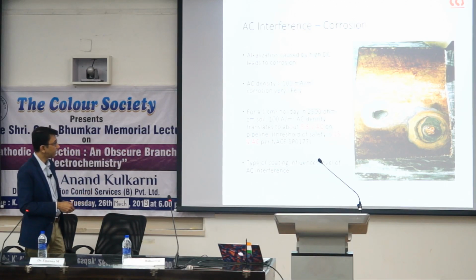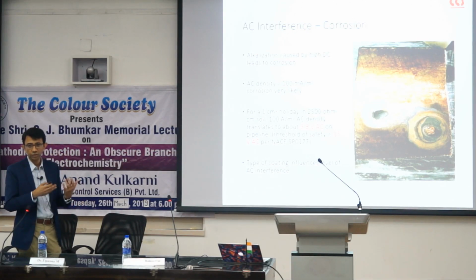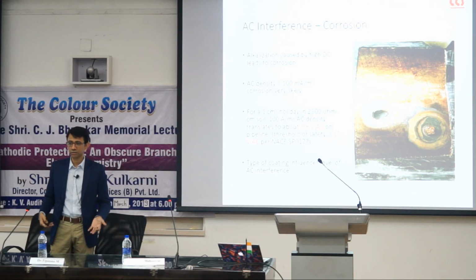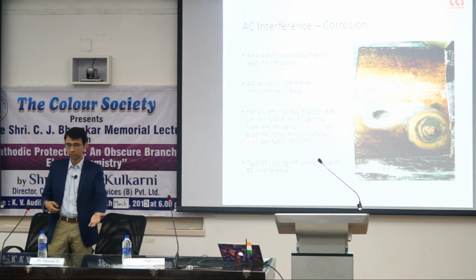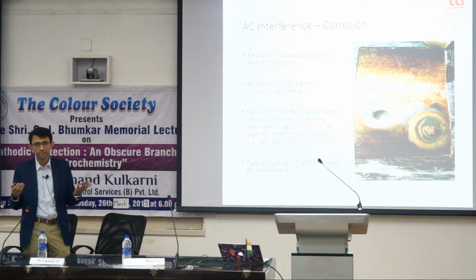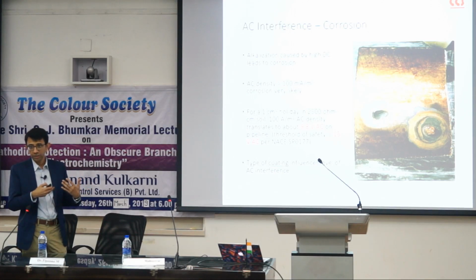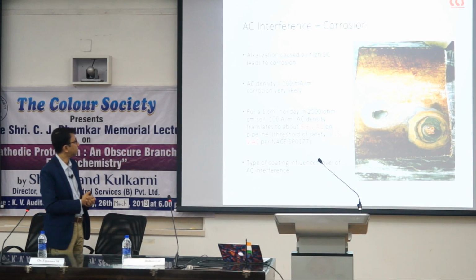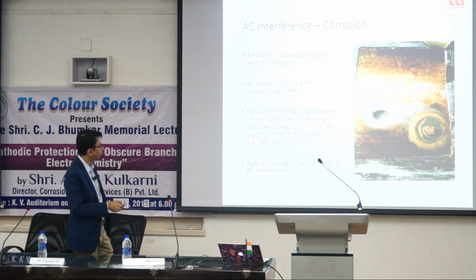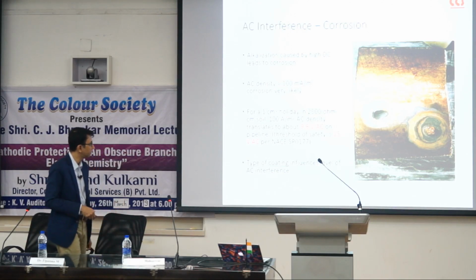So you have NACE SP177 talking about 15 volt AC as the threshold for safety. You cannot have a higher voltage than 15 volts. And if you interpret it in another way, if you look at a human body, 1000 ohm is my resistance. And if there is more current passing through me as a result of AC induction than 15 milliamperes, then it could lead to ventricular fibrillation, and that could lead to heart attack. Which is why you have 15 volt designated as the threshold of safety per NACE SP 177.